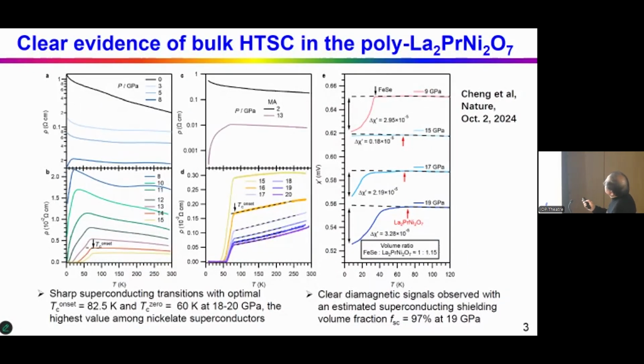About a week ago, clear evidence for the bulk superconductivity in this poly lanthanum 2 Pr nickel 2 oxygen 7 was reported. Okay, so that settled that the compound is a well-defined bulk superconductor in both resistance and also its Meissner effect. So I think this experimental group also showed why this is good: it stabilizes the double layer structure. Otherwise, you have some other 1-3-1-3 and 2-2-2-2 structures.